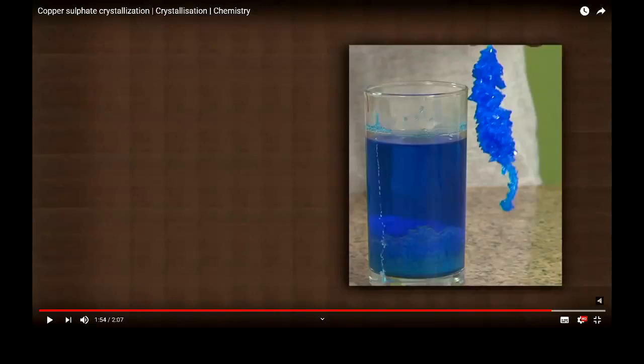What happens though, as this starts to fall out of solution, these initial precipitants would drop to the bottom. The crystal is typically got a higher density than the liquid. And those crystals can then act as nucleation points for further growth. So on the bottom of the container, this is probably what's happened to an extent. So we've had some come out homogeneously from solution, drop out of solution to the base, and then act as a nucleation site for further growth.